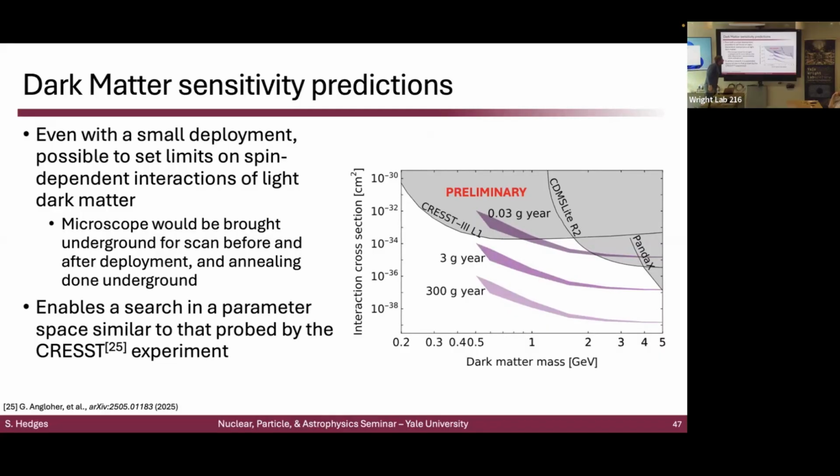I think this probably has to do with some uncertainty on what our actual threshold would be for these detectors. I'm not 100% positive that's what it is, but with the TRIM simulations, there's some scaling factor between the number of vacancies that TRIM predicts and the actual number of vacancies that you see in data. It's a factor of like 2 or 3. I think that might be one of the things that goes into this, but I'm not entirely sure what's setting the width of that band.